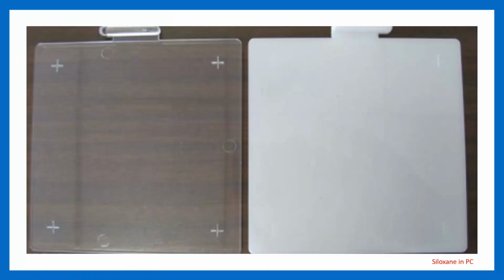So what does that look like? Polycarbonate on the left, you can kind of see through it. Almost looks like it might be a little hazy, but you can still see through it, it's clear. And then you can see on the right-hand side, the polycarbonate now has silicone in it, the siloxane that has been added, and it is no longer clear. And so, things to keep in mind.